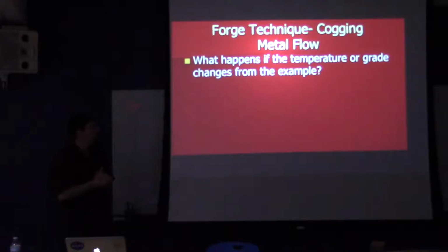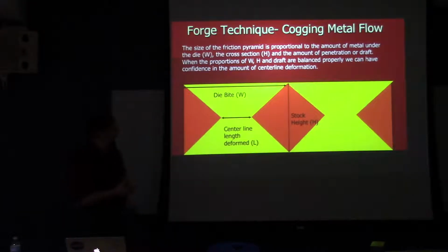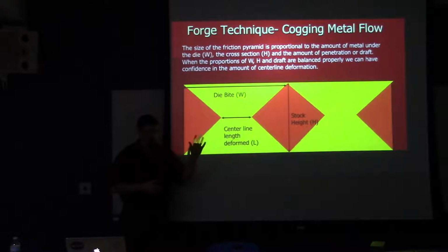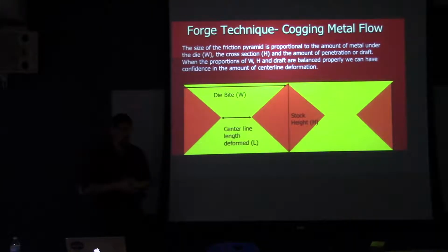So now, in this example, I should go back and give a little bit of background. These equations were arrived at through some research that was done not at Scott Forge, but somewhere else quite a while ago. I found it in a paper. In the particular situation that the investigator was researching, he was using a plain carbon steel, something like a 1045, and he was investigating temperatures between, say, 1900 and 2000 degrees Fahrenheit, okay? And I've used his research as the basis for what we do at Scott Forge because it allows us to have good, clear, relatively easy mathematical ways of quantifying what we're doing.